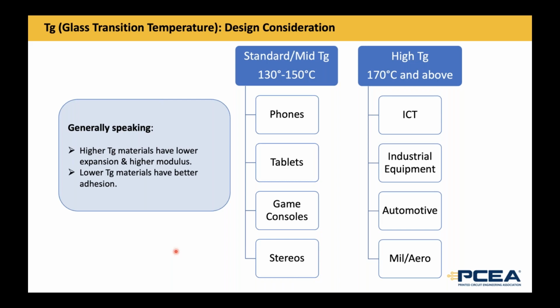For instance, for commercial applications such as phones and tablets, a TG of 130 to 150 degrees should be appropriate. But for applications that are exposed to high temperatures, like telecom applications, servers, or automotive electronics, you should look at materials that have a higher TG, over 170 degrees or so.